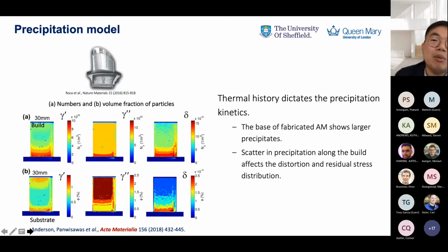So we take a thermal history from the lower length scale information to predict the precipitation kinetics, and then we will see that there is some in the as-fabricated condition. So the precipitation wavelength can be observed here. There is some large gamma prime, for example. This material is Inconel 718. If you want, you can follow our paper back in 2018. This is 4 or 5 years ago now. So we can actually understand why and how the build here is distorted and why the residual stresses are developed once we link this kind of result to the mechanical analysis.